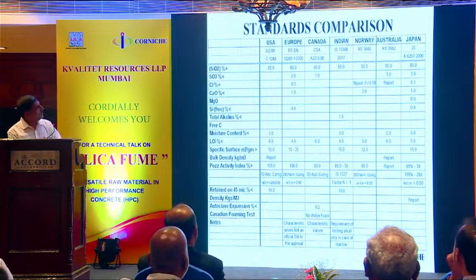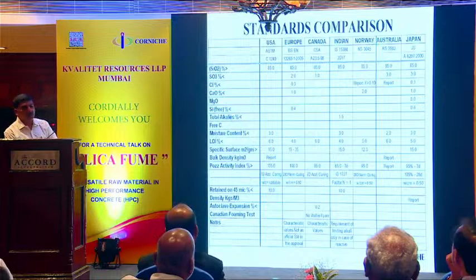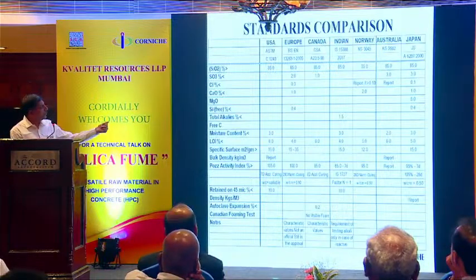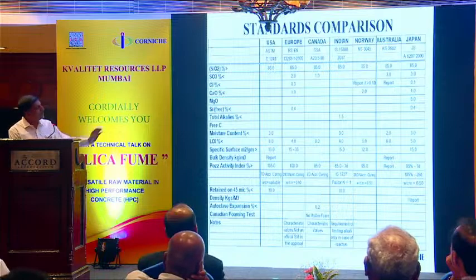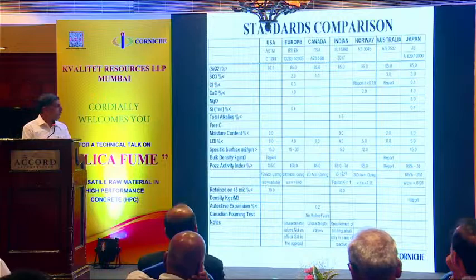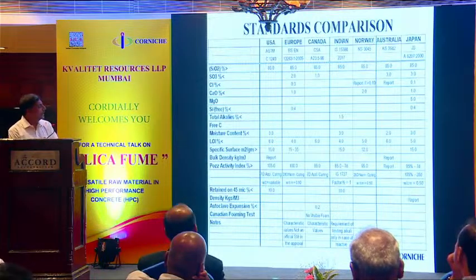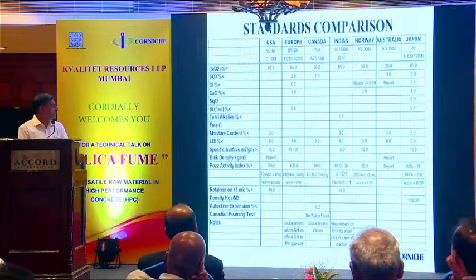Everything, if you see, requires a minimum amount of amorphous silicon dioxide, 85% minimum silicon dioxide. And the next thing I want to show is the loss on ignition and the alkalis. Loss on ignition, I think slowly they're trimming it down further. It should be less than 6%. And the specific surface area, it asks for minimum 15 meters square per gram. And pozzolanic activity index, ASTM asks for 105%, and our Indian standard asks for 85%.